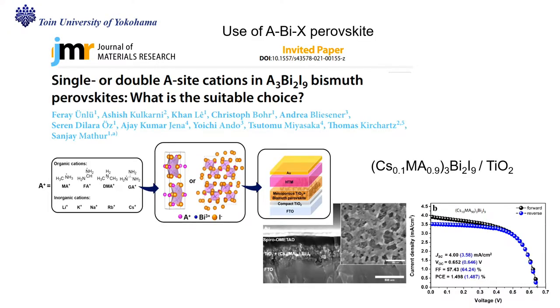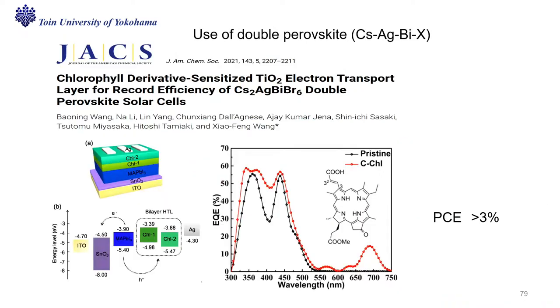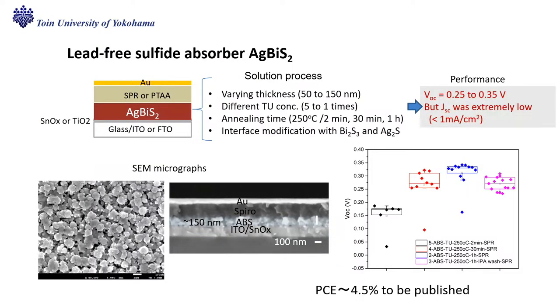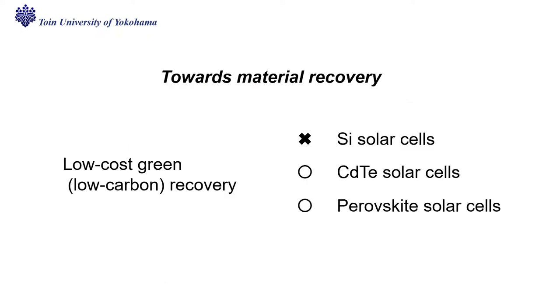We also studied the lead-free new materials. Yes, we have to finish now. This introduces a chlorophyll derivative sensitizer, TiO2 electrode, absorbed by the cesium silver bismuth bromide, free of lead. This is also a new material. It's unpublished data. We are now submitting this paper. This is silver bismuth sulfide, one solution coating process. And further,